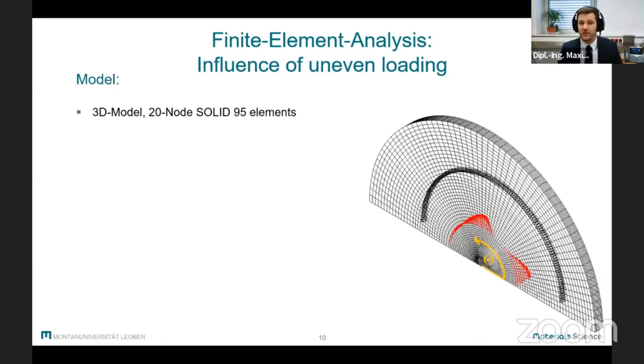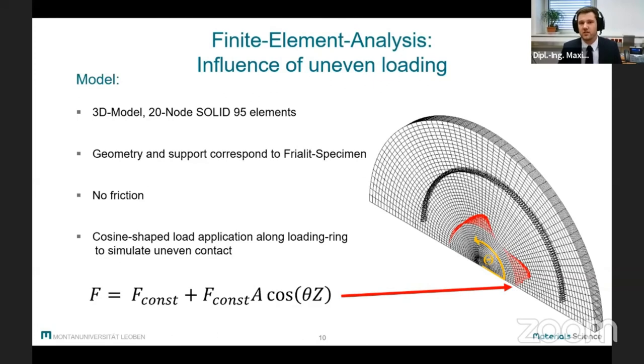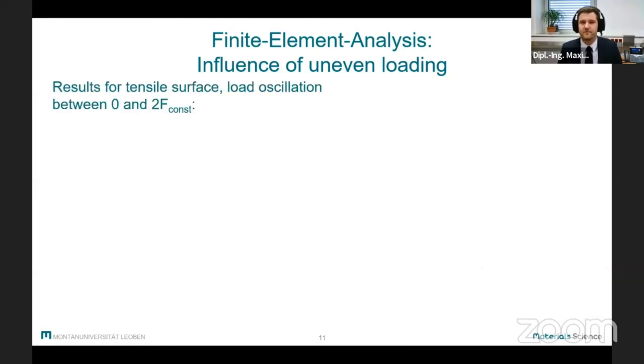We used finite element analysis again, but this time with a very simple three-dimensional model. As before, the model corresponds to the tested samples, but this time friction was not taken into account. To further simplify the problem, instead of contact calculations like in the previous model, a cosine shape load was applied to simulate multiple contacts.